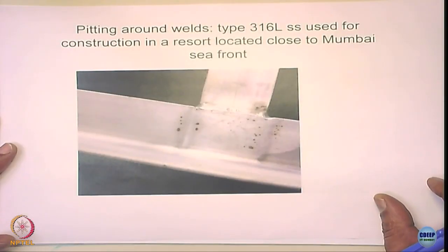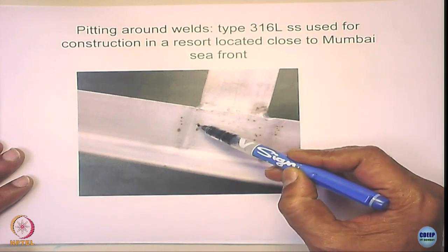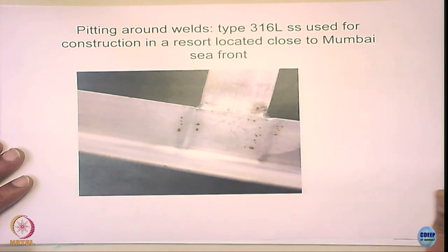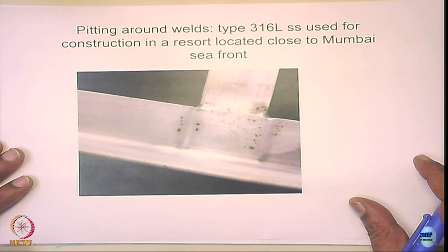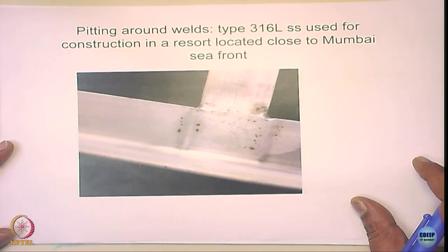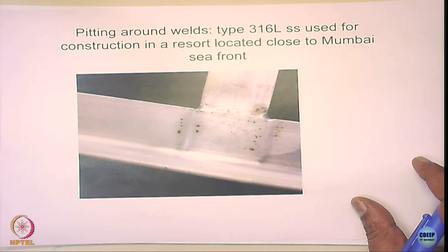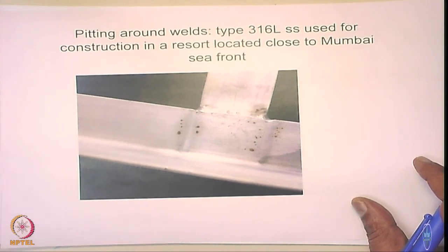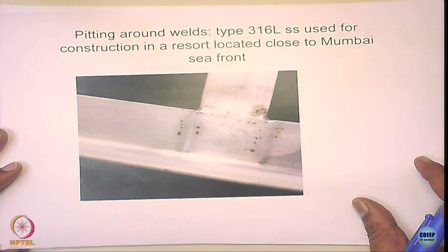They become very severe where they were welded. See that here, right? I hope you were able to see these reddish brown spots, okay. These spots do correspond to severe pitting. Two kinds of problems here. One is the loss in the structural integrity, the other is the cosmetic appearance of the stainless steels, right? You have reddish brown color, and especially if you are talking about household appliances or the facades of a house, it can cause appearances which are not really acceptable.